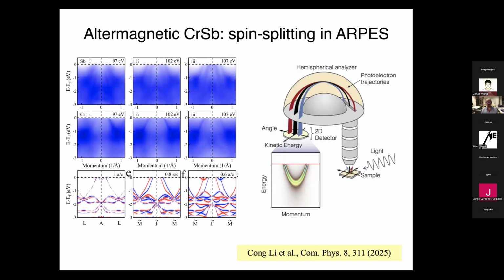Okay. Is this measurable experimentally? The answer is yes. The spin splitting is actually observed in ARPES. So ARPES is light shining on the sample, or X-rays, or UV. And electrons come out, and you measure, let's say, the band structure. Well, in this case, you can really say that you measure the band structure because correlation effects are not very large. And for different incoming energy of the photon, you will measure at a different kz.